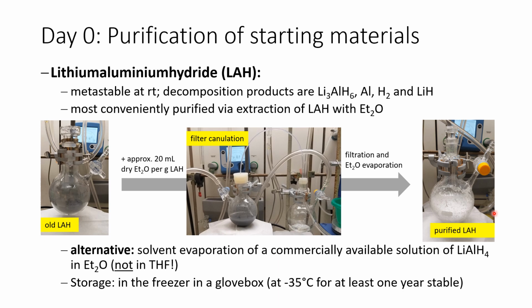Another way to get a very pure lithium aluminum hydride is to buy a commercially available solution of LAH in ether. Here it's important to not buy a THF solution because the THF will coordinate the lithium in the LAH. To store your purified lithium aluminum hydride, you should use a freezer in a glove box. In our experience, it is stable for at least 1 year at minus 35 degrees.